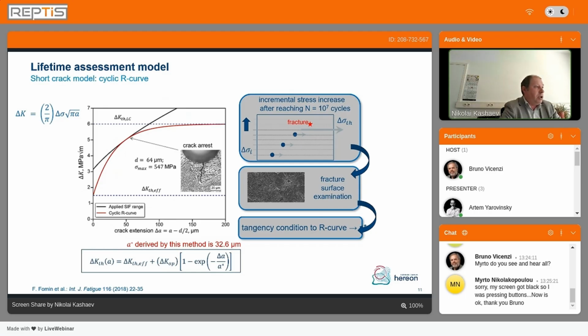Here the picture shows what we have in the case of a laser welded component. And you see that in components that did not fail, if we analyze them, we are able to identify fatigue cracks growing from internal porosity, which were stopped, for example, at grain boundaries. This metallographic cross-section shows exactly this case. And it is somehow the evidence and indication that the concept of fatigue strength does not mean that we have our component without defects. It means that we have defects, but the possible fatigue cracks from these defects will be stopped. And the condition of fatigue strength is exactly the condition of crack arrest.